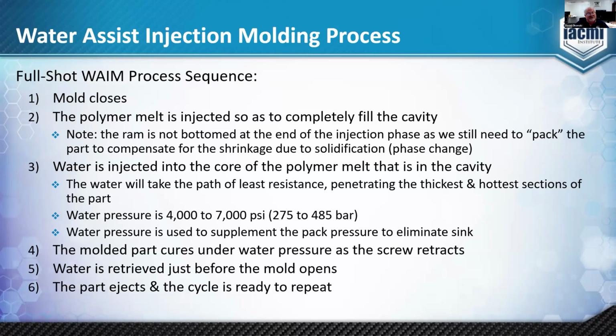In the full shot process, the mold closes and the polymer melt is injected to completely fill the cavity. So it's more like the conventional molding process where you're filling to 95 to 98% of full before you start to release the water. The ram, of course, is not bottomed because you're still using polymer pressure, hydraulic pressure, to pack out the part. But water is injected into the core, and again, it will take the path of least resistance. Water pressure will be between 4 and 7,000 psi.